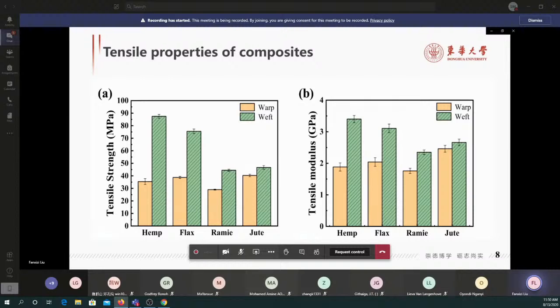It's obvious that the crimps of the 4 fabric composites were significantly larger in the warp than in the weft. Among them, hemp and flax weft yarns had little crimp, ensuring a high utilization rate of the fiber strength, and the crimp angles of ramie and jute weft yarns were about half of those in the warp yarns. This could effectively increase the tensile strength and moduli of the composites in the weft direction.